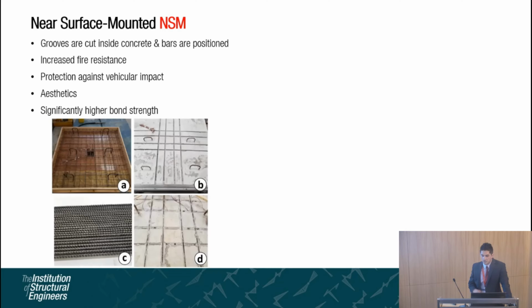The major advantage of this method as compared to the externally bonded method is, initially we did some testing of bond test, and this was found to be more than 200 to 300% stronger bond strength as compared to EBR. They have increased fire resistance because the FRP is protected inside the concrete, and it's aesthetically pleasing, specifically in the region of the car parks where there is the negative moment. It will be protected against accidental damage from the cars and tire damage.